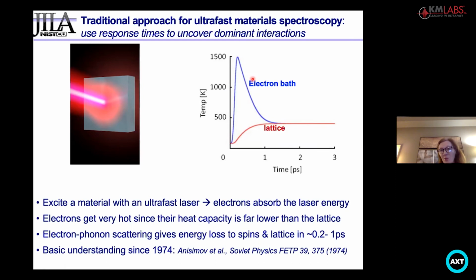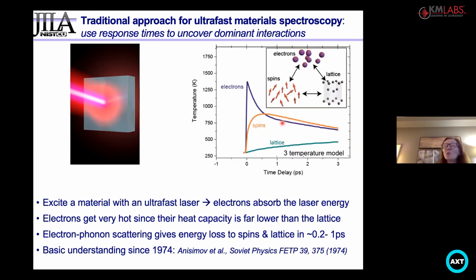When you heat a material with an ultrafast laser, the heat capacity of the electron gas is much smaller than that of the lattice. So, as shown here, their temperature spikes, and then with electron phonon coupling, the lattice heats up and the electron bath cools in about a picosecond or so. And that understanding has been the norm since the mid-1970s. And this understanding was also assumed to be true in magnetic materials, where the electrons absorb the energy and then lose energy to the spins in the lattice through different coupling mechanisms.